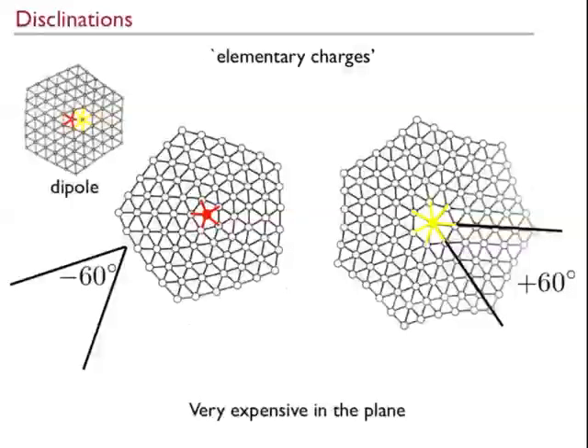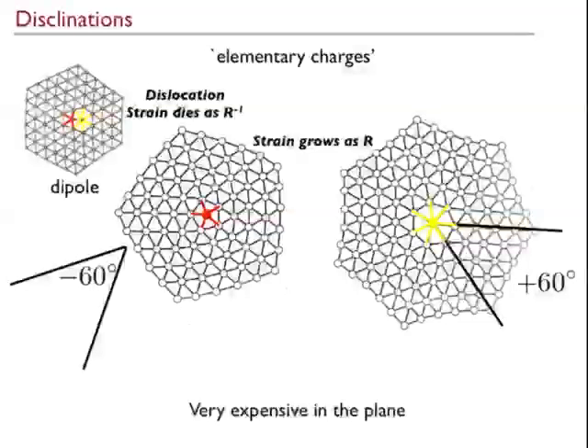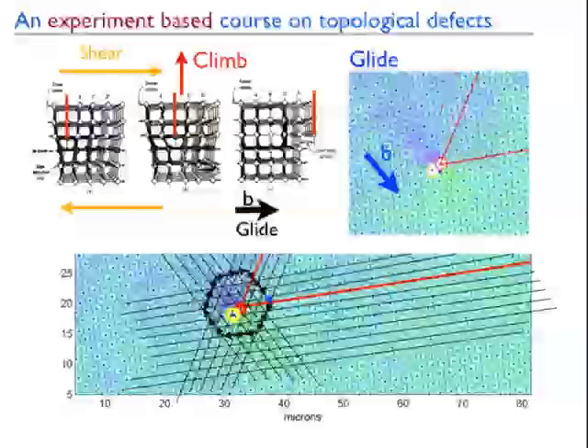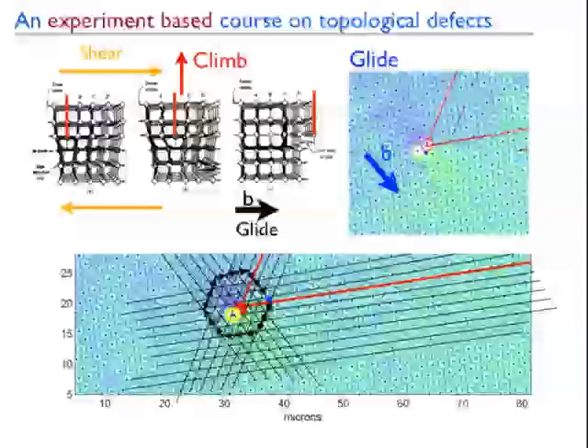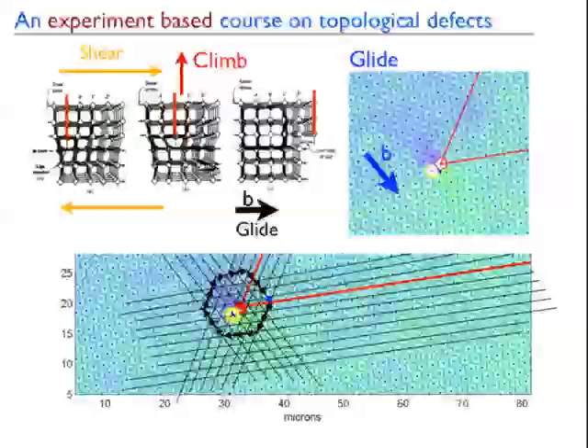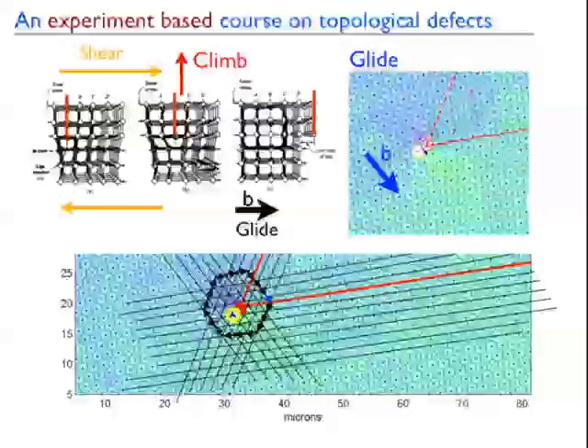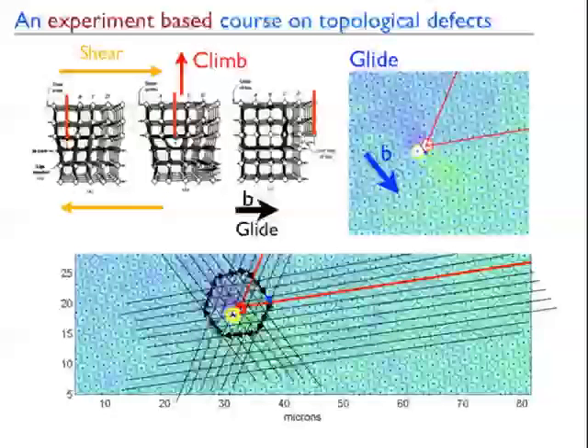If I put this topological charge with this topological charge, the 7 and the 5, I cancel this out to lowest order, and I get a dipole, which is the dislocation we're looking at. That has a strain field that dies as 1 over r, and which integrates to log. These guys are very important for typical crystals because they give it plasticity. That's why they were invented.